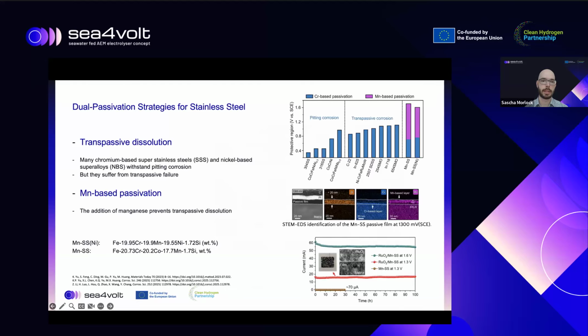please. One example that you can see here for enhanced passivation is when you add manganese. As you can see here on the right-hand side, this purple bar indicates that the window that can be used for working in seawater is increased significantly by the application of this manganese-based passivation. On the right-hand corner and in the lower graph, you see that if there's no catalyst, we don't see any current, and as soon as we add the catalyst, we also see a current. That means in principle the basic material is stable. Next slide, please.